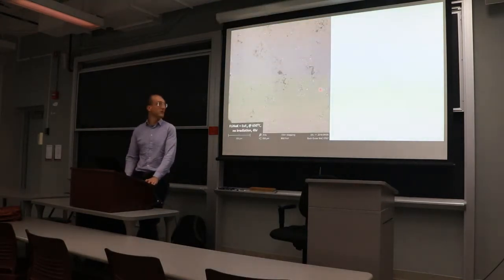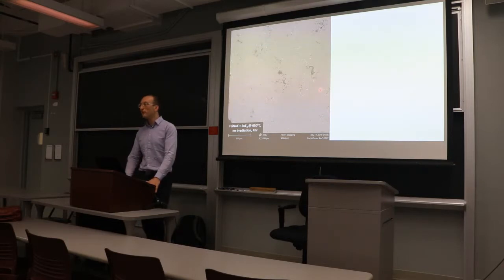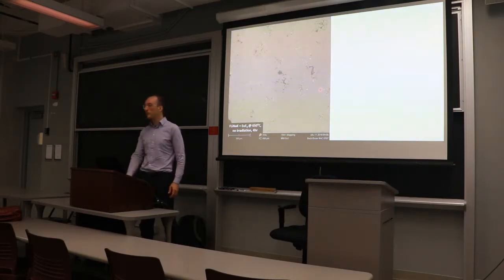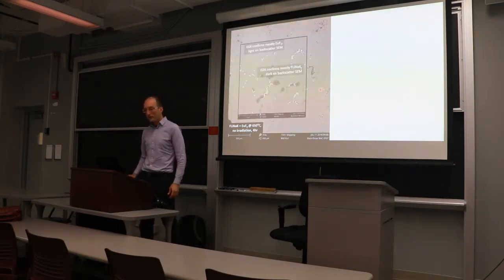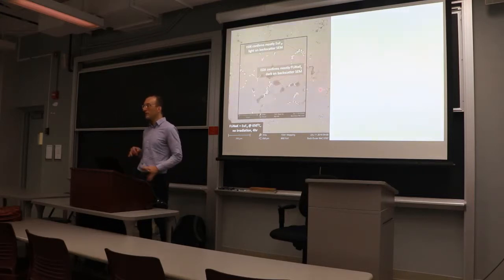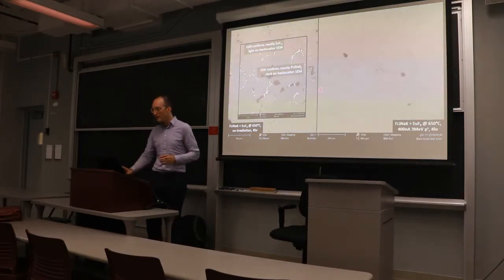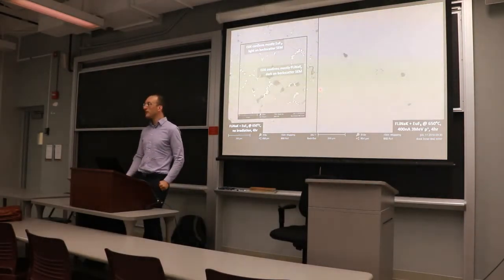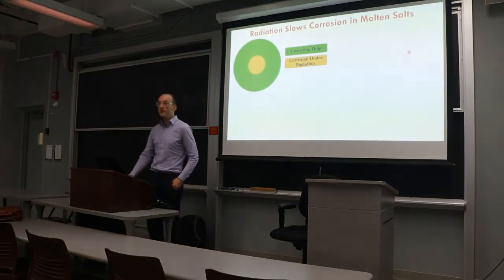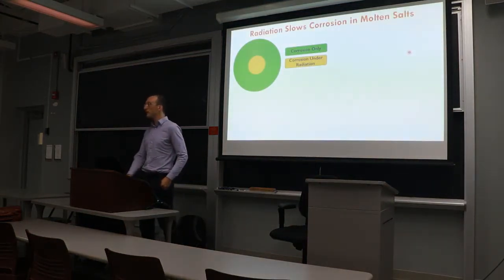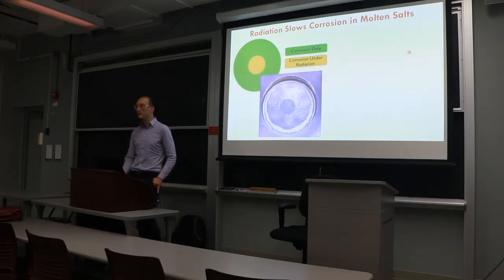If you look at the unirradiated side, you can see a mess, where after 4 hours, the salt has penetrated through the 25 microns of foil, and you can actually see molten salt creeping and oozing between the grains as one would expect to see. When you move over in the SEM and look at the irradiated side, it comes out clean, except for the occasional impurity and one grain that we found where the salt did penetrate through. So the effect is actually so strong that you can see it with the naked eye. In fact, this picture was taken with a cell phone.